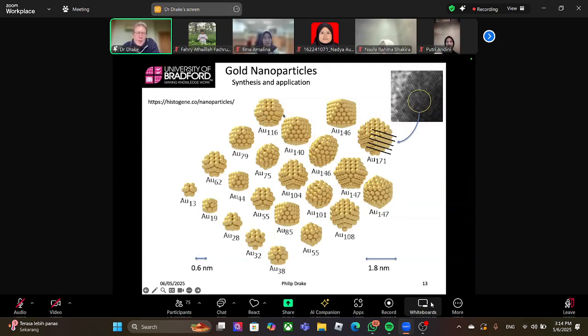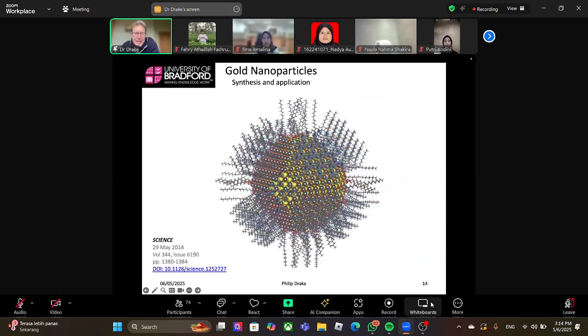These are gold nanoparticles. We never see them like this in solution. These are bare surfaces, just gold atoms on the surface. That doesn't exist. You cannot have a bare atom on the surface. There's always a stabilizing ligand on the surface. And this is something people often forget, but nanoparticles have to have a stabilizing surface. So in reality, what you see is the gold atoms underneath, but then on the surface are the ligands.